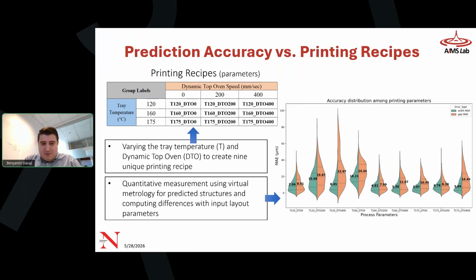So you can see our prediction accuracy is within single digit, sometimes less than 20 micron for 150 micron structures, and each side of this violin plot shows width measurement versus gap measurement, and you can see similar accuracies. And for different recipes, we learn how to measure this differently.